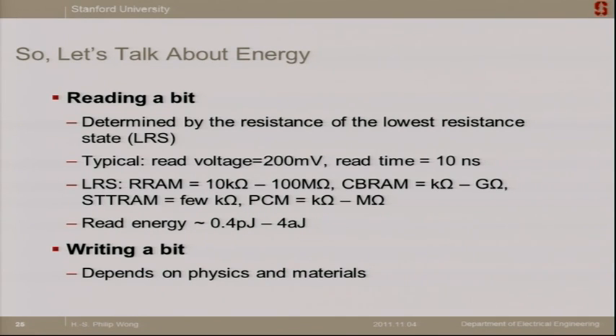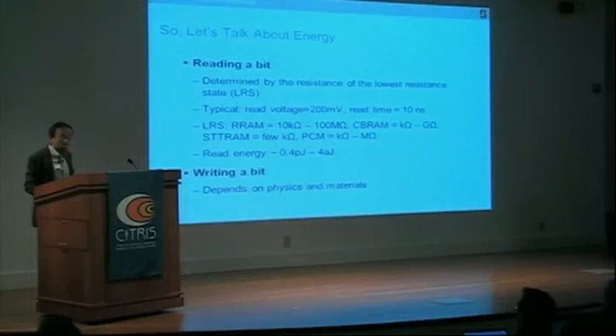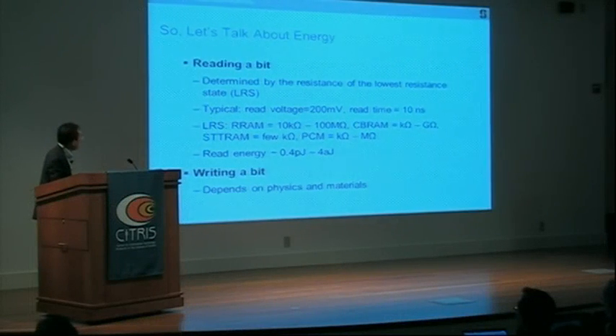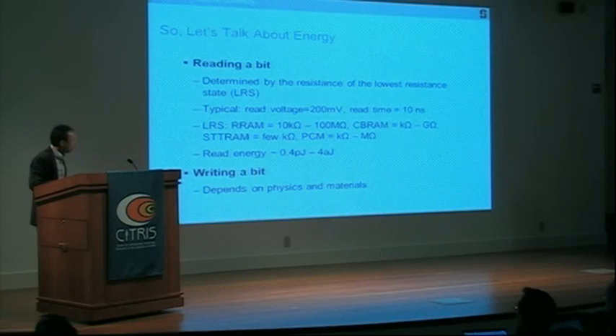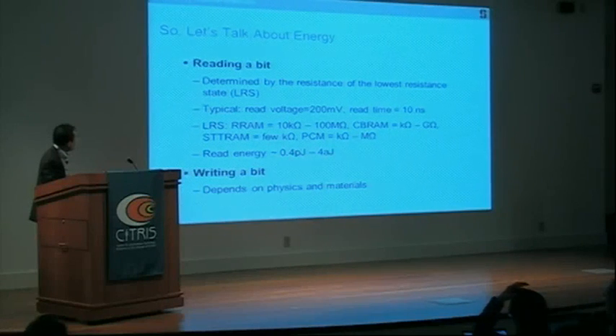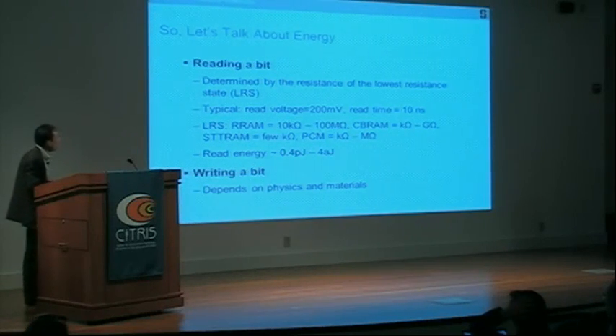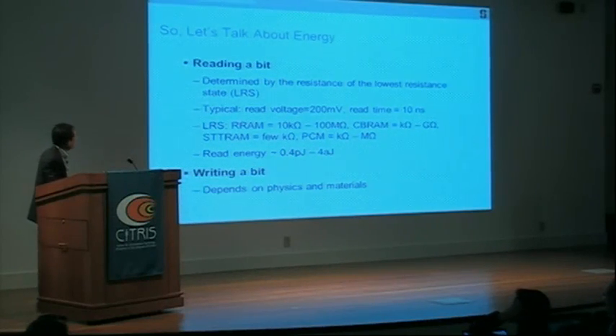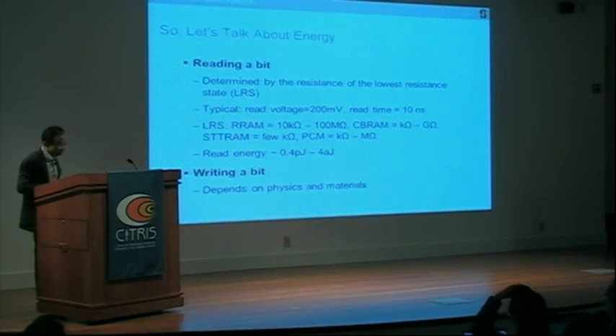For the STT-RAM and the phase change memory, it's more a function of the physics of the materials and the way the resistance works. So there is a little bit less range in here. Phase change memory tends to be of the order of kiloohms to megaohms, and the STT-RAM is a few kiloohms. So as you do this math, the read energy spans from about 4 attojoules to about 400 attojoules, depending on the value of the low resistance state.